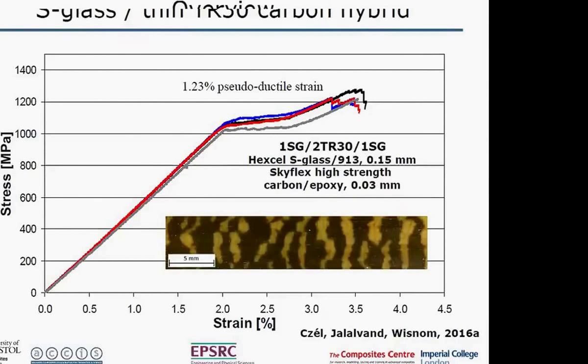One of the other things which is interesting about this type of material is that you get this striped pattern here. So the material is originally black. When it fails, you can just about see these cracks in the middle of these regions here. These are the cracks in the carbon, and then you get a little bit of localized delamination, and that produces this stripe pattern. Because once you get a bit of delamination associated with those carbon fragments, then the interface within the material reflects the light, and you get this yellow pattern.